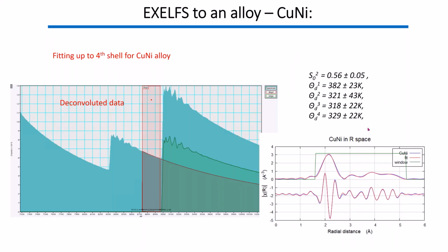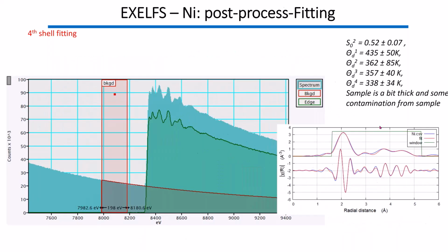Yeah, from the filter point of view, but there's one more thing I want to mention. This is a technique which is very sensitive to sample contamination. At 80 or 60 kV, it's a bit more sensitive to the sample surface, so it also requires proper sample preparation tools. But it's good to try, to be honest. We did plan this, but we haven't reached that stage yet, but we will certainly try this at some point.